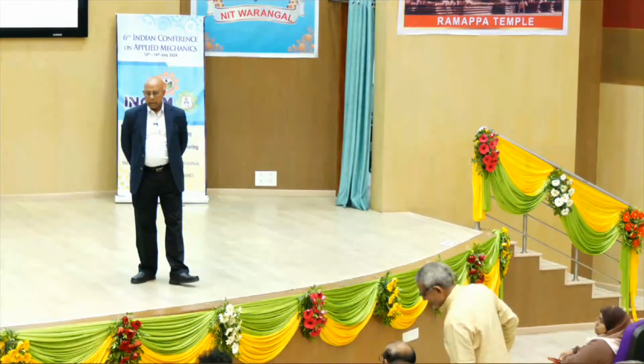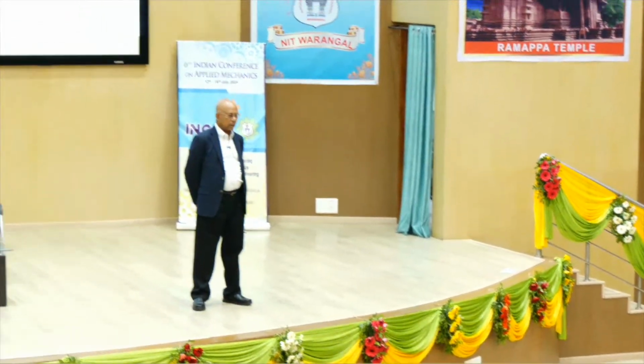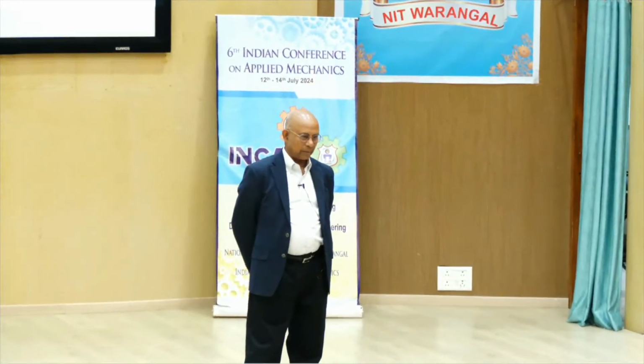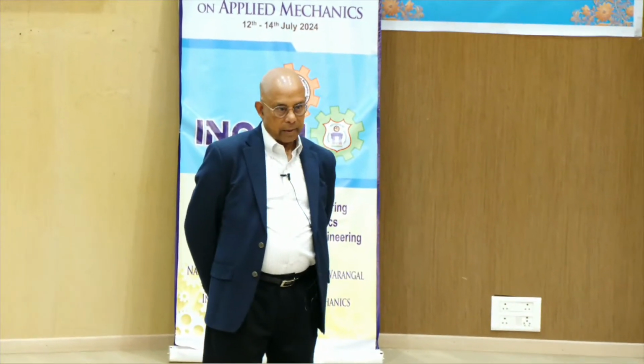Yeah, sure. First of all, let me tell you, Dr. Lakshman Rao, that you cannot go away from empiricism. Empirical models will exist forever. Unfortunately or fortunately, many empirical models, if they are calibrated properly, you can predict within that range like you mentioned. If the applied pressure is 5 times more than the pressure and the strain rate is 5 times more than the strain rate, then what happens? You get into trouble. You are extrapolating, but in some cases it may work if it's saturated at a certain strain rate and it's not changing much after that, then you are okay. So you have to be careful.